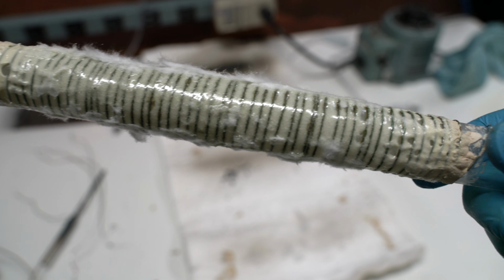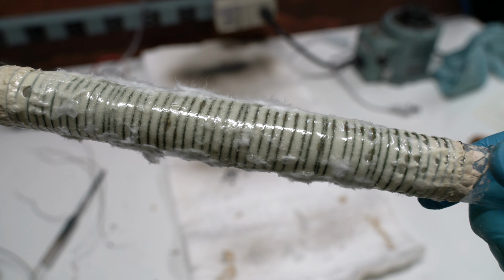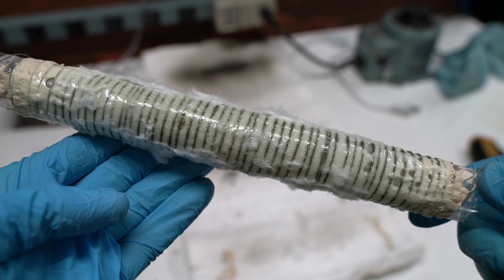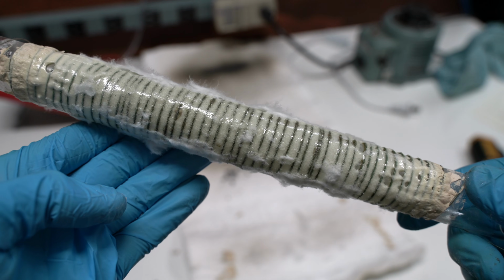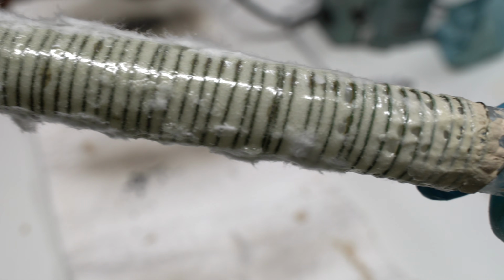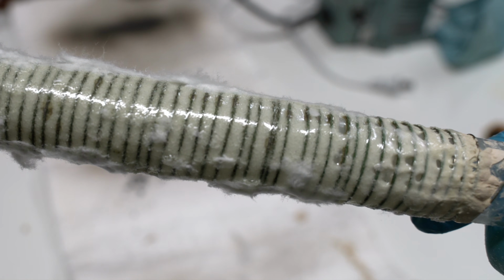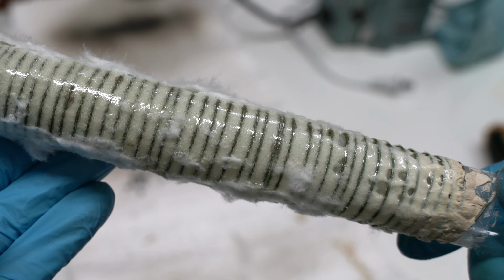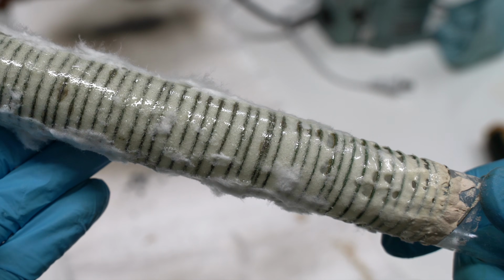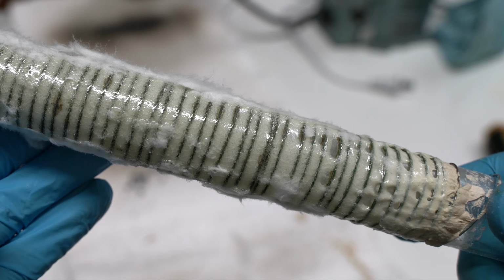Back on the workbench now, I'm going to unroll the insulation and check how the tube is doing. You can see how the high temperatures have converted the grainy sodium silicate cement into a shiny glass, and the heating element is now embedded inside. I can see that a few of the coils are a little bit too close together, and I'm pretty sure that was just an error when winding the coil and not a problem during the firing. I'll be a little more careful next time.